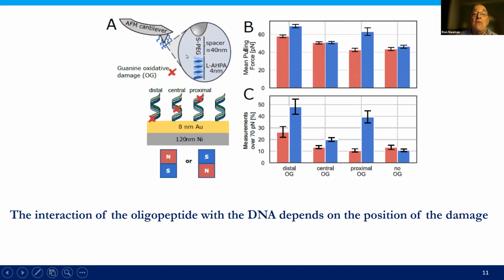And that's really interesting because now we can come with an AFM to which we attach an oligopeptide here. And the idea is to measure the force between the oligopeptide, which is modeling an enzyme here. So we have an alpha helix oligopeptide here, and we measure the force between this alpha helix and the DNA, the different DNA with the different damage. So you realize that if there is no damage, there is very little force. However, the blue and red are the forces with the magnet pointing up or down respectively. So you realize that when we have damage, first of all, the force increases, but the force depends on the position of the damage.